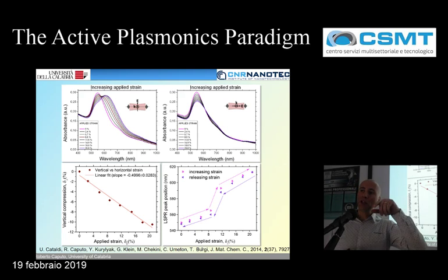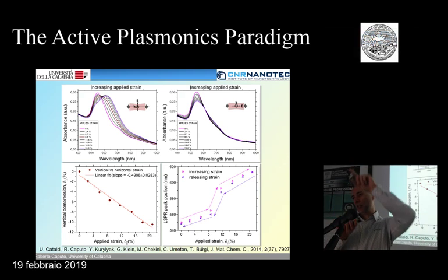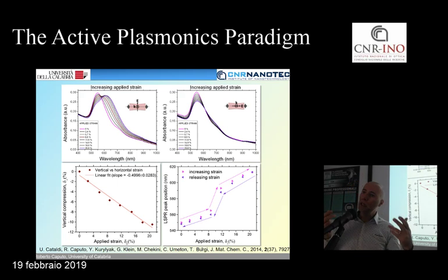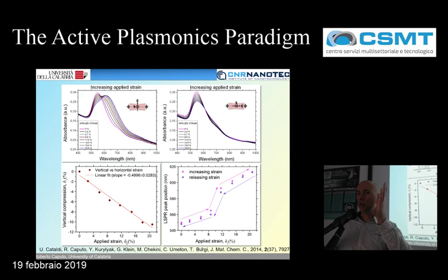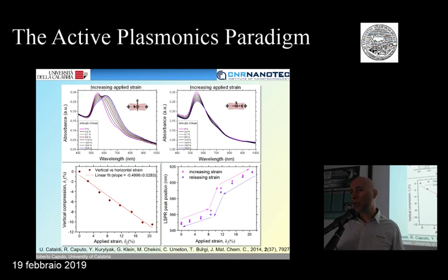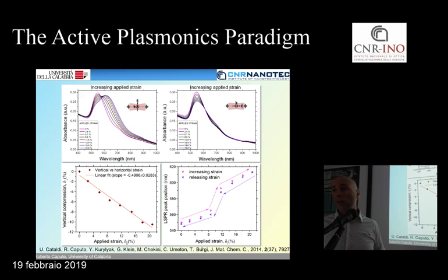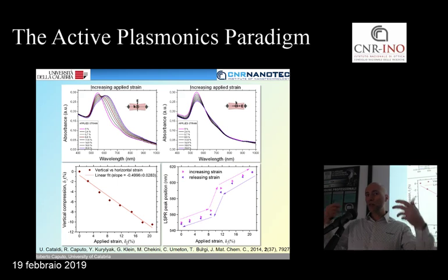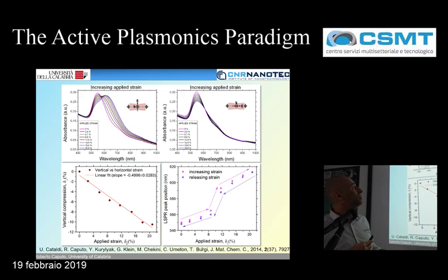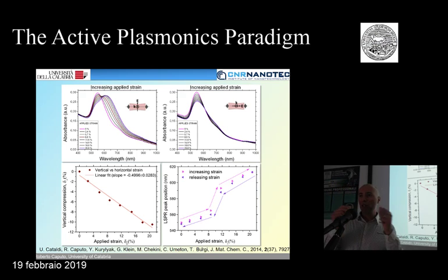But the particles which are situated vertically, let's say, with respect to the stretching, are influenced in a way because they are coupled to each other. Other particles instead are going away from each other, depending on how they are located. So I suppose there is a family of particles which keeps the original plasmonic behavior because they are simply not coupled to each other, and these belong to the first peak. But the amount of these particles, once you stretch, decreases, and the result is that this peak is also decreasing accordingly. On the other side, the number of particles which get coupled during the stretching action is also increasing while you increase the stretching.